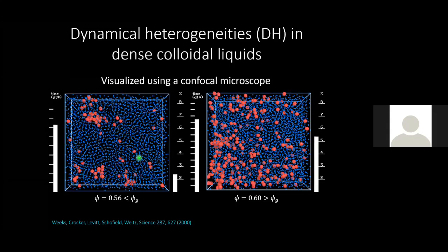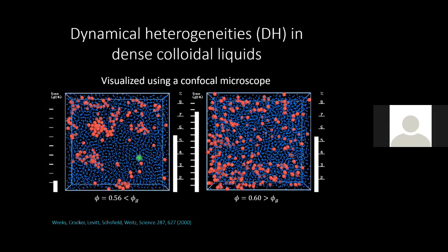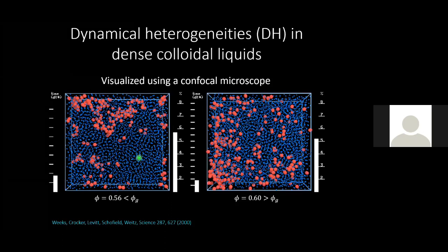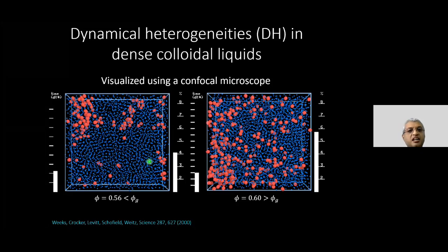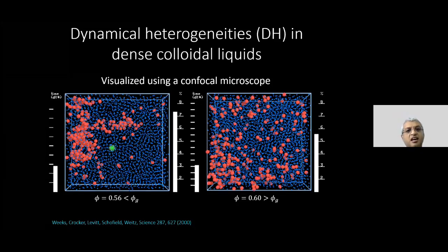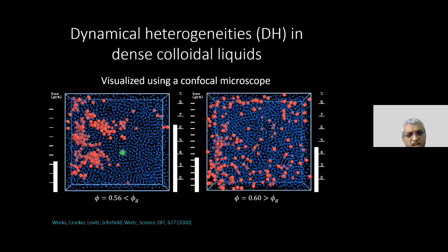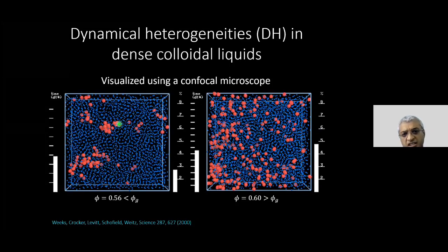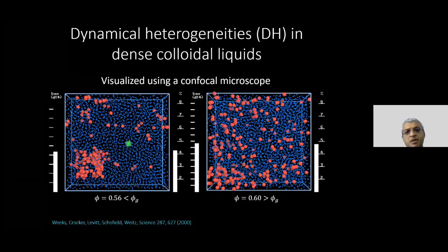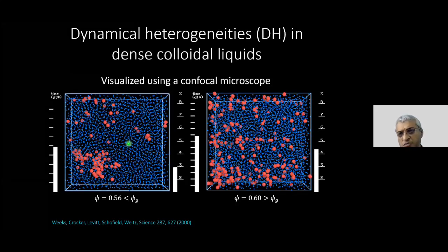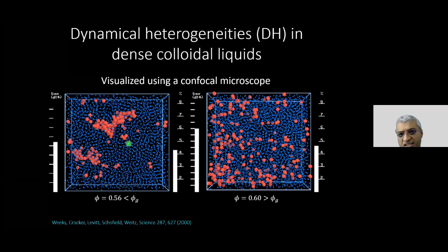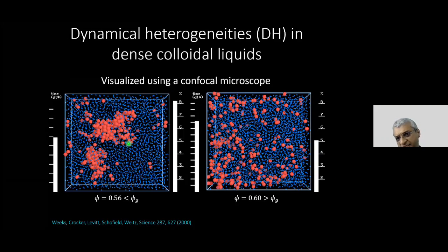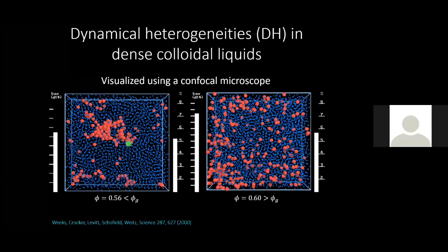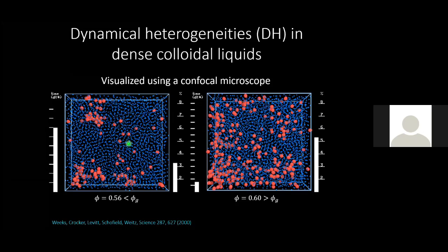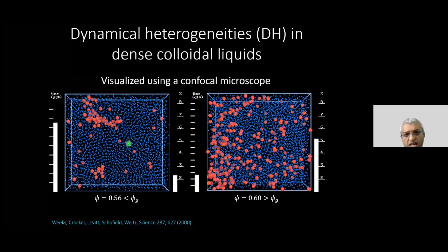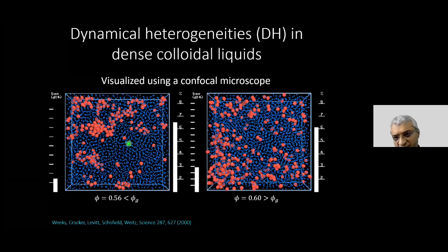Just wanted to clarify, are all the hard sphere particles of the same size? Okay, it's a very good question. The thing is, to get into the glassy state, if you take monodispersed particles, there would be a very high propensity to form a crystal. So this is a system of bidispersed spheres. But people have also done very dense hard sphere systems in which you form a crystal, you stir it up and get into a glass. So both experiments show similar dynamics. So the bidispersed one is more likely to form a glass? Yeah. Because you've turned on frustration, you are very likely to end up in a glassy state. Thanks.